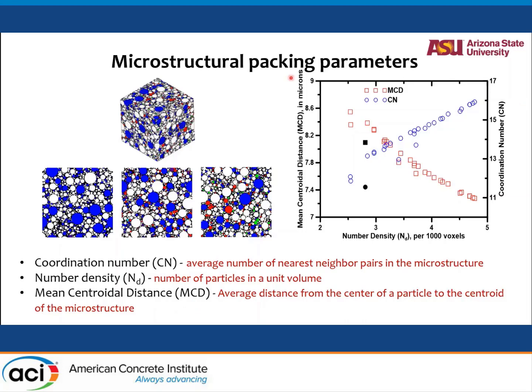So here is the mean centroidal distance, number density, coordination number, plotted as a function. So as number density increases, your centroidal distance comes down, obviously, as you expect. Your coordination number, or number of neighbors, goes up. Simple relationship that you can come up with for all the mixes that we have evaluated in this work.